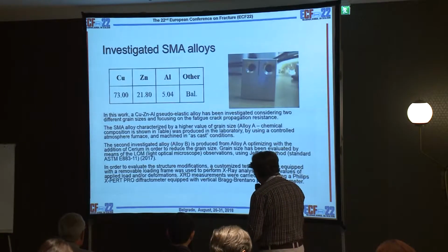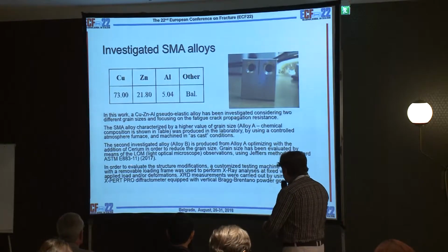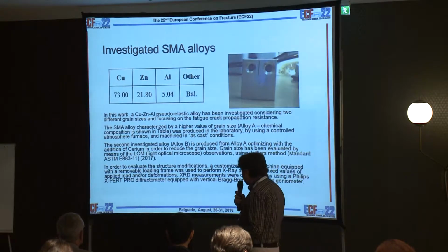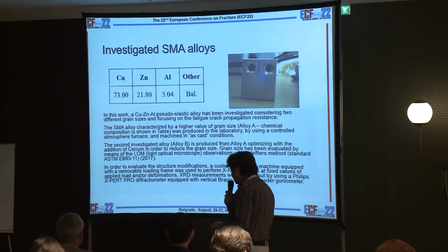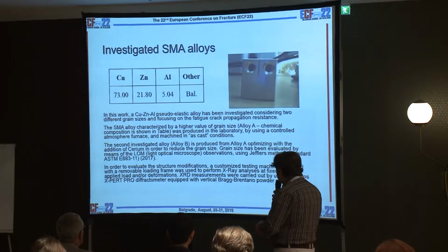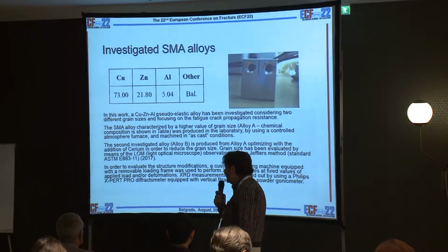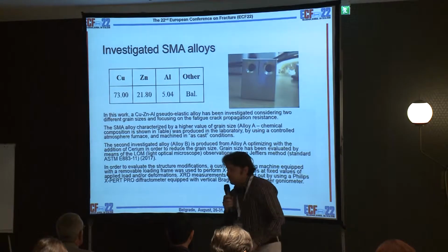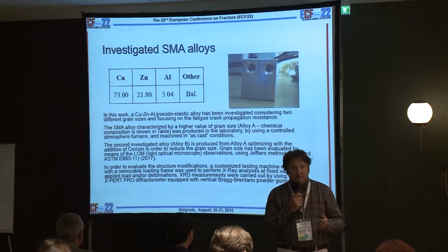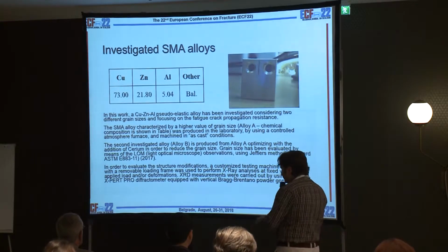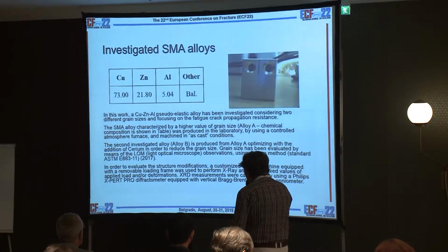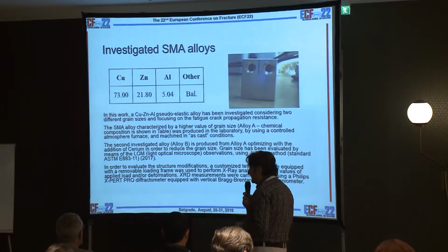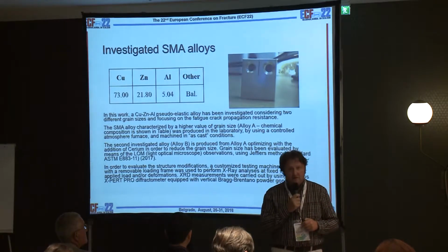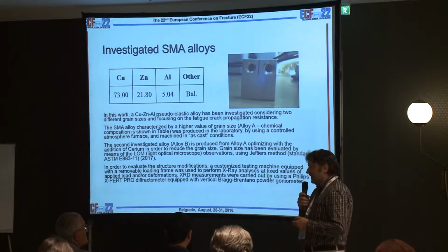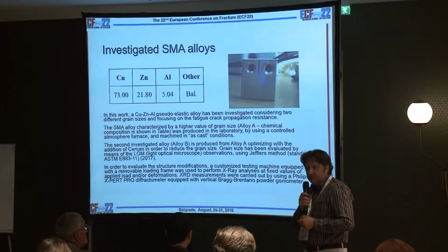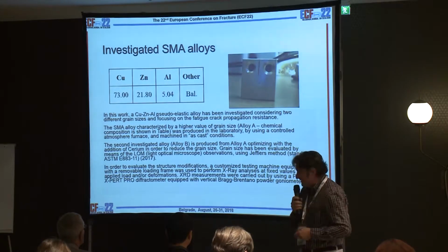The material produced in our laboratory is characterized by this chemical composition. We can see 73% of copper, 21.80% of zinc, and a high value of aluminum, 5.04%. Other elements are used to balance the chemical composition, without cerium. I named this alloy, in this work, alloy A. The second alloy has the same chemical composition, but in the balance elements we used 0.25% of cerium in order to obtain a refinement of grains.